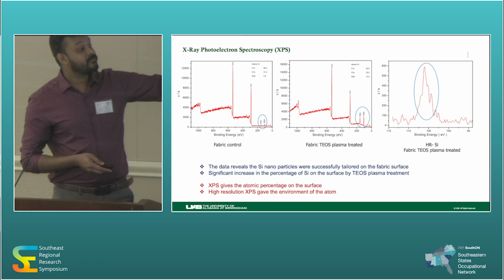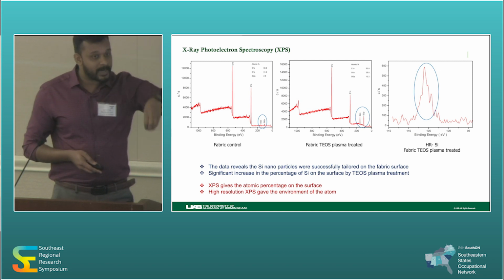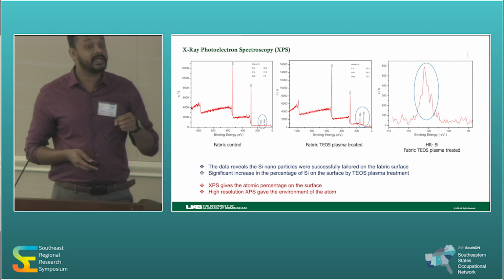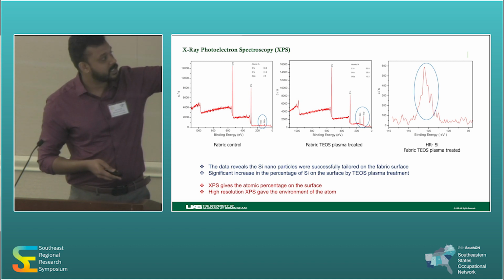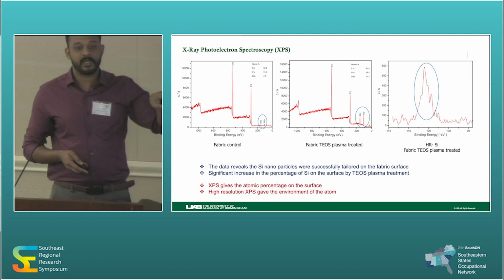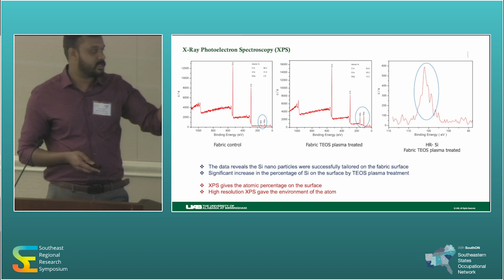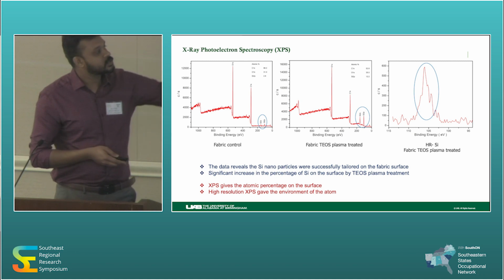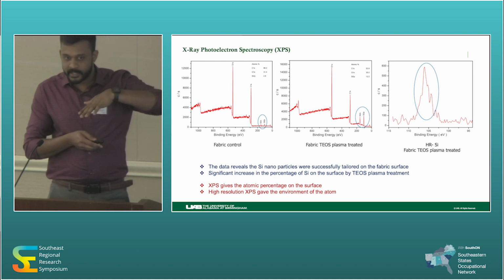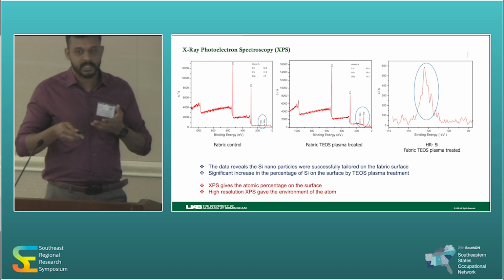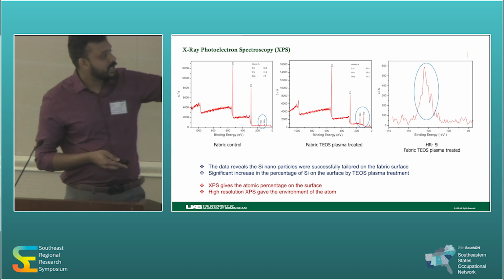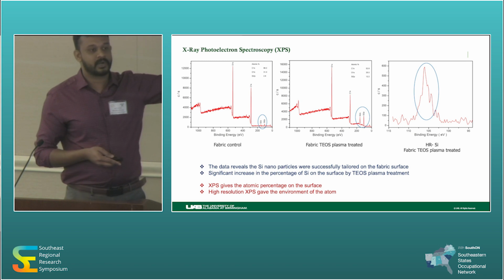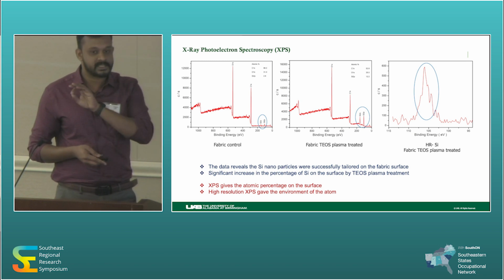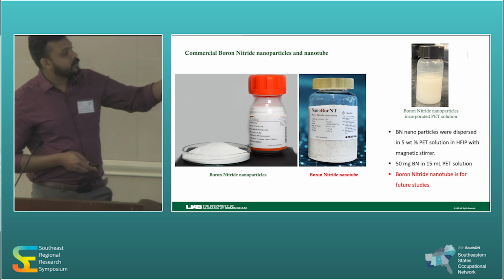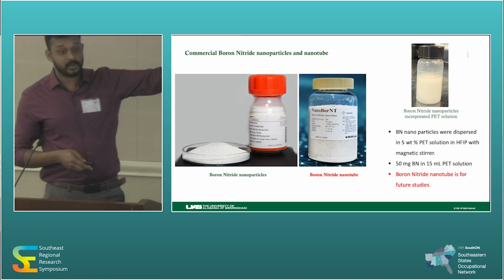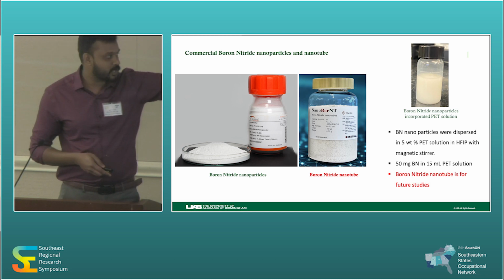Then the environment of whatever material you are implanting on the surface can be analyzed by high resolution spectroscopy. With that high resolution, in the third one, we have a significant peak of silicon 2p, which relates to the orbital. So silica is successfully implanted on the fabric surface, and we need to try the thermal reflection experiments later. From the XPS data, it is clear that our plasma treatment with TEOS is effective. Then this is the boron nitride nanoparticle, and the next step is going to be boron nitride nanotube. That's why I marked it in red.